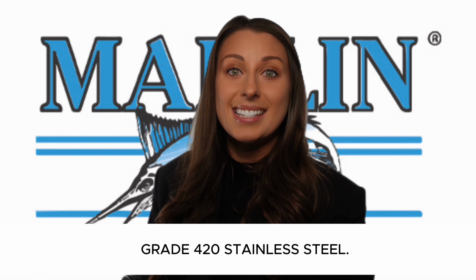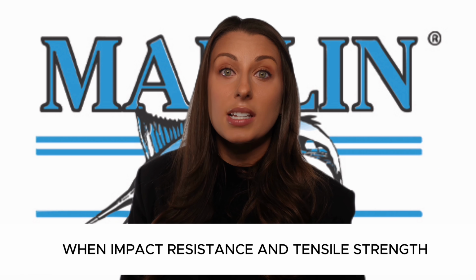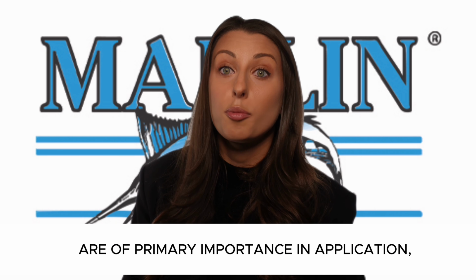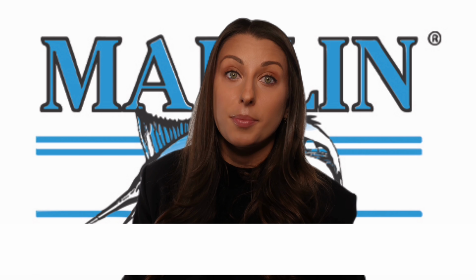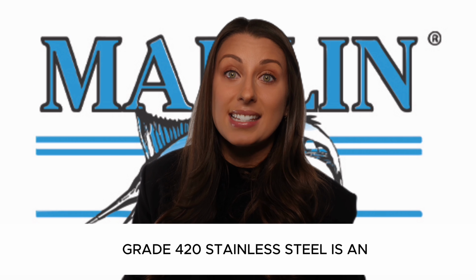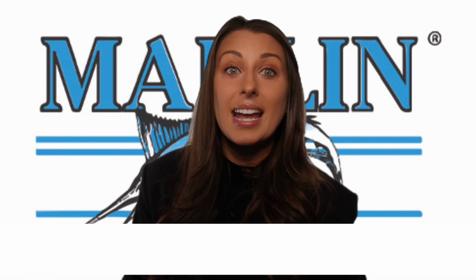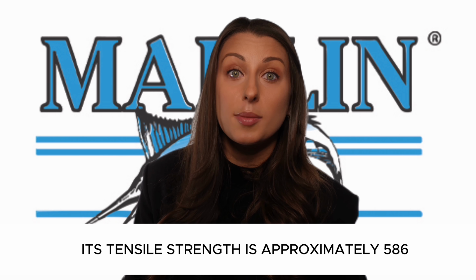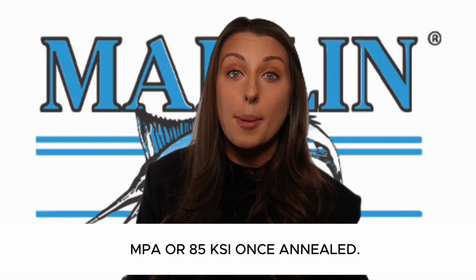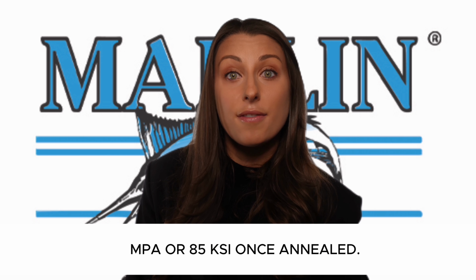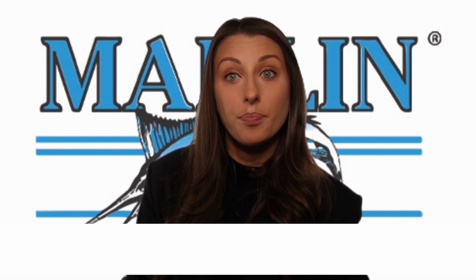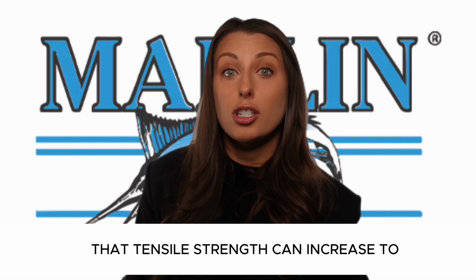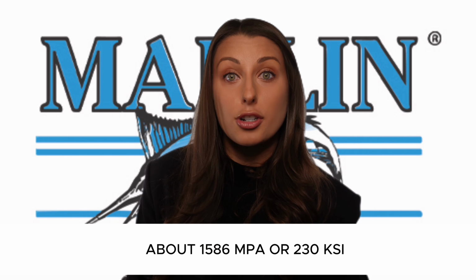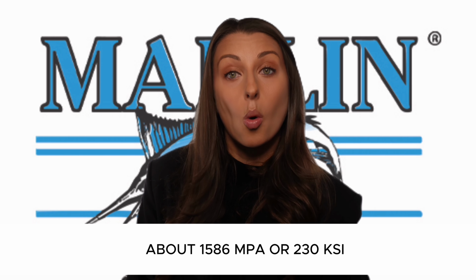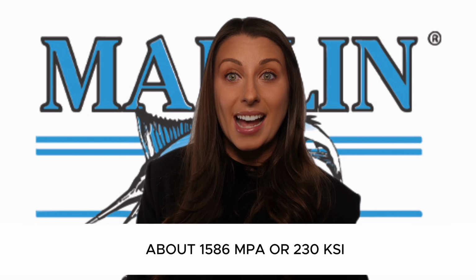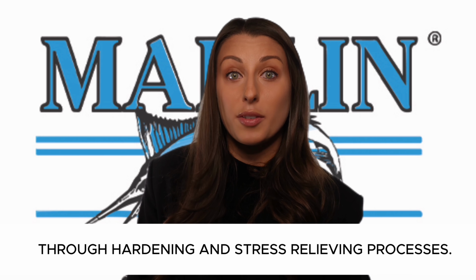Grade 420 stainless steel. When impact resistance and tensile strength are of primary importance in application, grade 420 stainless steel is an ideal choice. Its tensile strength is approximately 586 MPa or 85 KSI once annealed. That tensile strength can increase to about 1,586 MPa or 230 KSI through hardening and stress relieving processes.